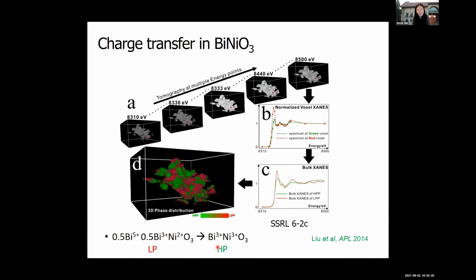And so you can follow these changes by looking at the nickel K edge. With 3D spectroscopic imaging, you can see how the sample is transforming in 3D, and then follow this kind of pressure-induced redox reaction in 3 dimensions with pressure.